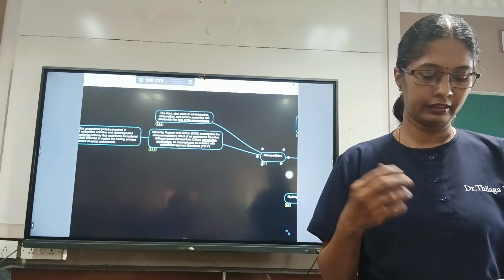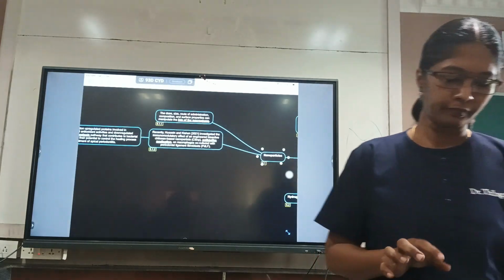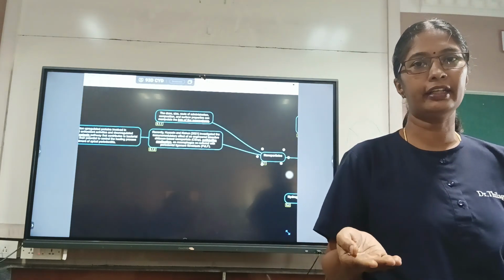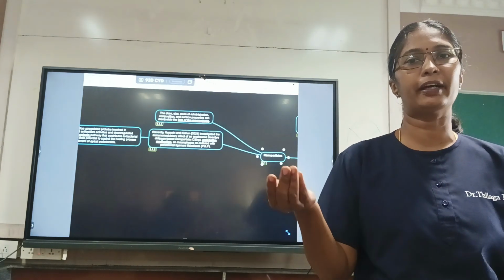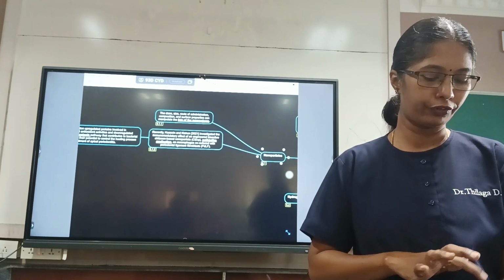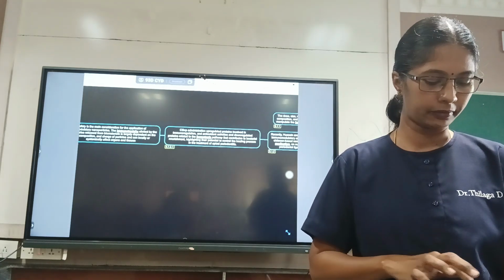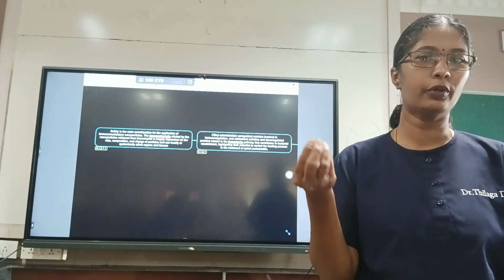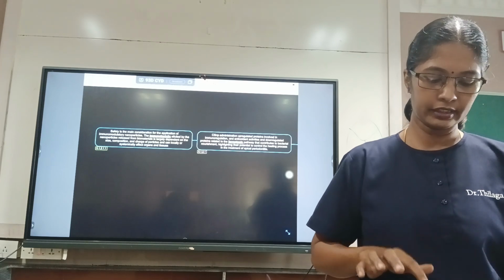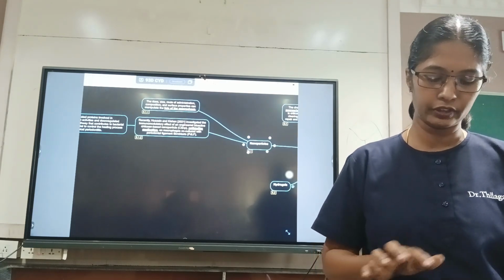A study developed an antibiotic medication using chitosan-based nanoparticles, which were co-cultured with periodontal ligament fibroblasts and macrophages, and they found that it shifted the M1 phenotype to M2 phenotype by studying the cytokines released during the co-culture. And one disadvantage of nanoparticles is that, depending upon the size, composition and charge of the particles, it can cause immunotoxicity in the local area or in systemic tissues. So this is one disadvantage of using a nanoparticle.